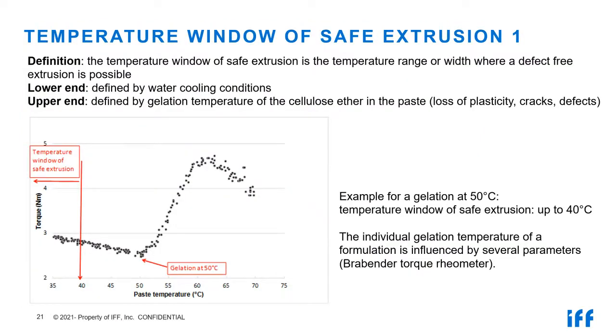So now we are coming to a very big and important topic, which leads to a serious understanding of every individual paste you are formulating. I mentioned already that a limit of all extrusions is the gelation of the cellulose ether. This is a very unusual property. Normally, if you heat up a solution of any ingredient, let's say sugar or salt, the solubility increases with the temperature. But here in the case of cellulose ether, it's exactly in the opposite direction. At a certain temperature, the solubility is decreased and the cellulose ether starts to flocculate out of your solution. And if this happens in a ceramic paste, you can't see it anymore because of the invisibility of the ceramic particles, but it happens. And this is a high danger for your extrusion process.